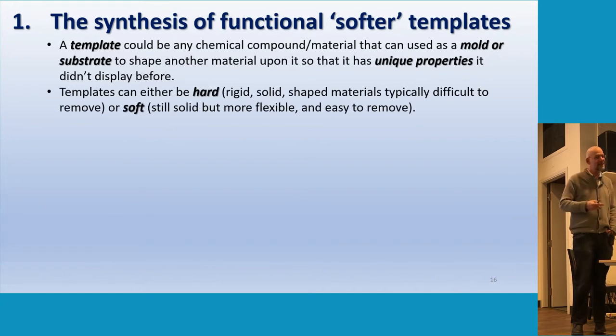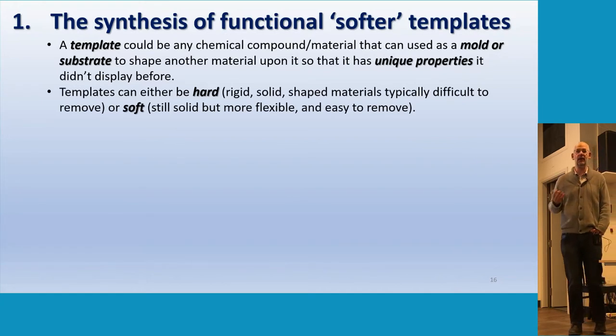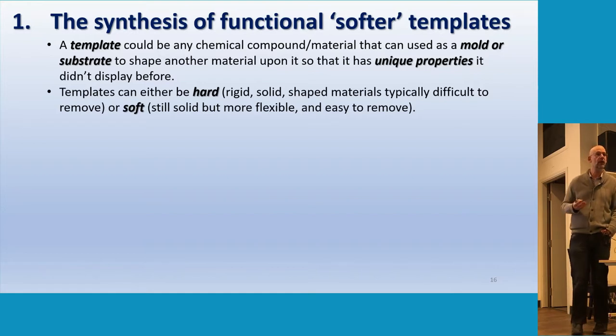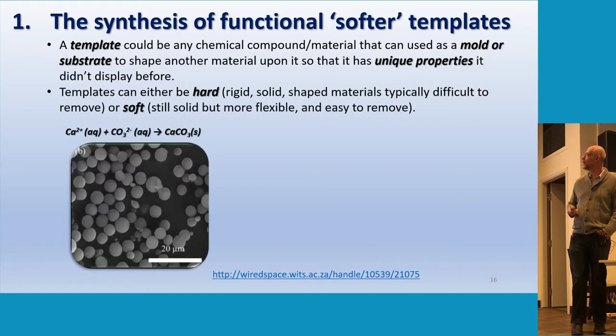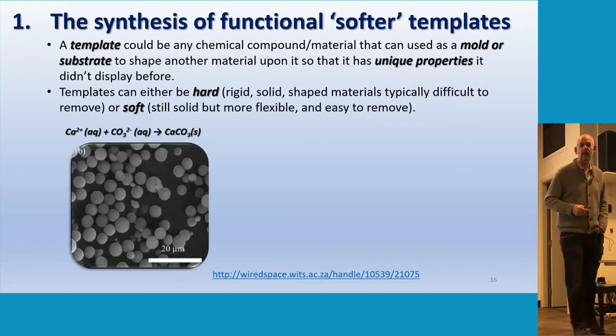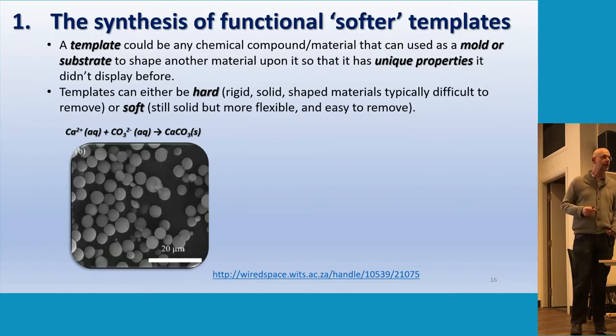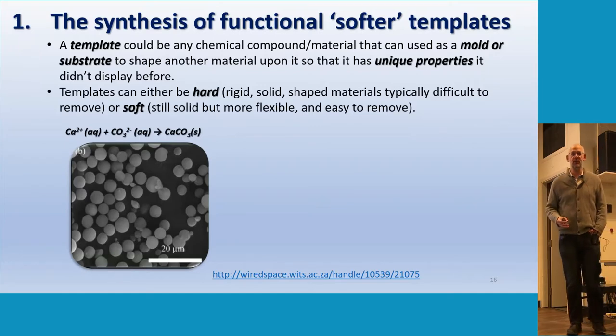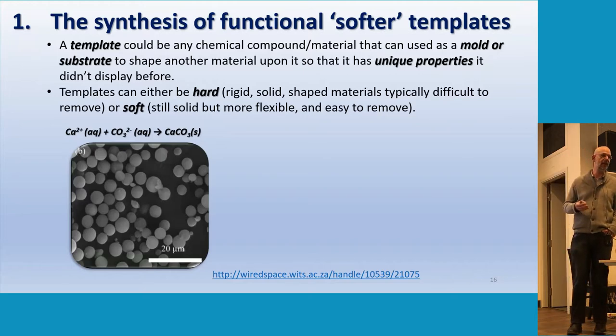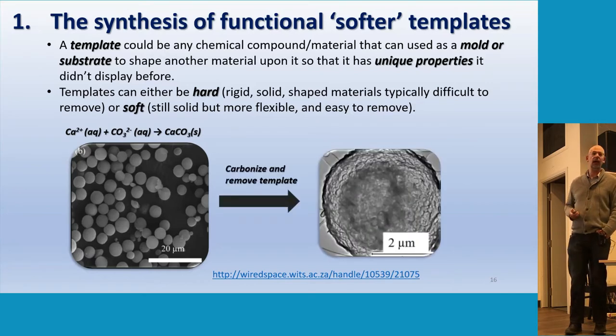Templates could be hard, difficult to remove, but they retain their structure, they're thermally stable, they're chemically stable and so on. Or they can be softer, more flexible and easier to remove. In previous research, what we did is we took calcium carbonate. You take calcium ions, carbonate ions, and precipitate them. It's a straightforward precipitation reaction. You use a directing agent, usually a surfactant of some kind, a soap, and it directs the structure. You see over there these nice little spheres. Once you have that, you can carbonize them, put them in the presence of a carbon vapor, and they form these wonderful sphere-like structures. They are 2 microns, so they are bigger than nano. But this is one of those where we've actually removed the template.